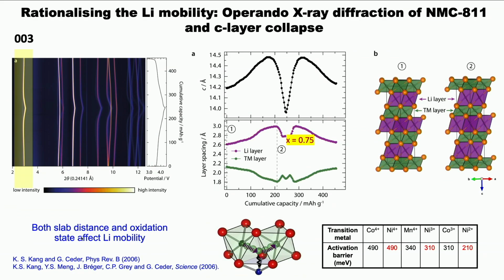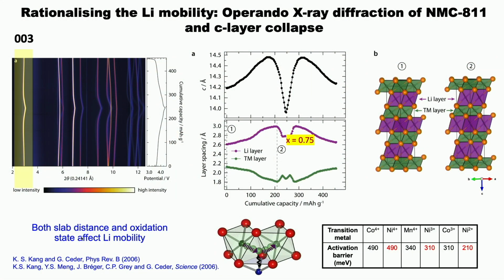And we can get an activation barrier for that transport by just varying the temperature. So there's 2 points. Why do you get increased mobility? One is that the layers increase, and then at the end they collapse. And so that collapse is why you actually stop moving the lithiums at the end of charge. There's another phenomenon which I worked on with a former collaborator who may be familiar to some of you in the audience, Gerd Ceder. And that's associated with the charge of the ions on the layers and above. And if you oxidize your nickel from 2+ to 4+, if I'm a lithium ion, I'm hopping from octahedral site to tetrahedral site to octahedral site. There's a very short contact there, and that short contact gives you the activation barrier, and the higher the oxidation, the bigger the Coulombic repulsion. So this all makes sense.